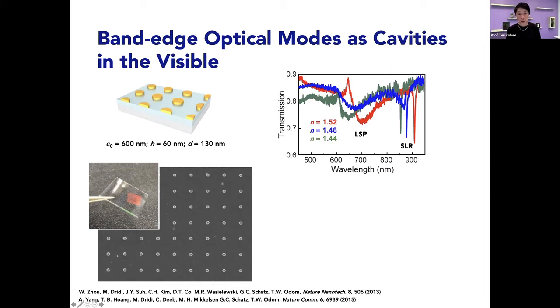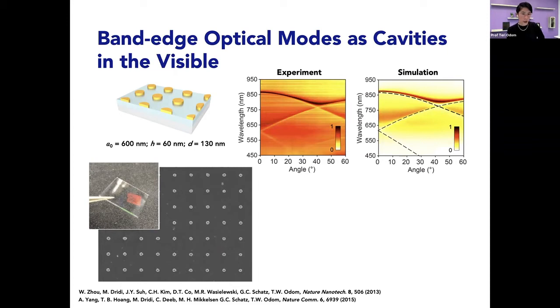You can take advantage of an individual particle property or the collective property of the array. And as you might expect, as you increase the refractive index around this array structure, both of the resonances shift to longer wavelengths. So we can take these normal zero order spectra and change the angle of incidence. What I showed you earlier was just a slice at theta equals 0. And then we can stitch them all together over very large angles, and we need large area samples to be able to do that. And we can construct the equivalent of optical band structures. And you can see that based on simulations, they match, they're amazingly consistent.